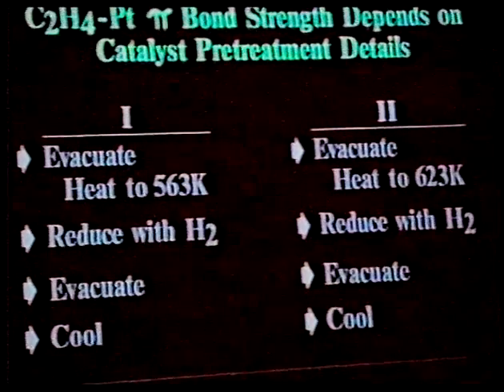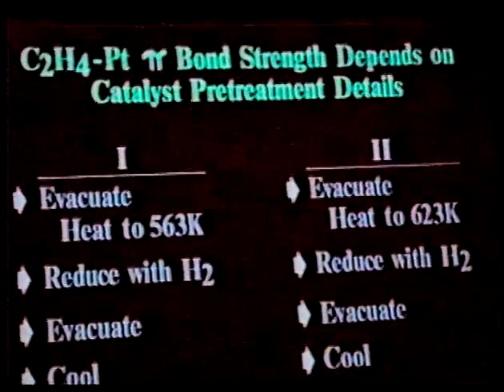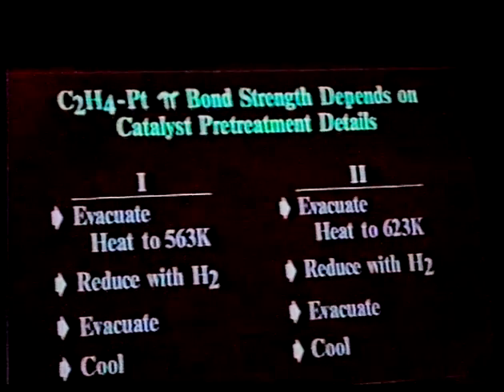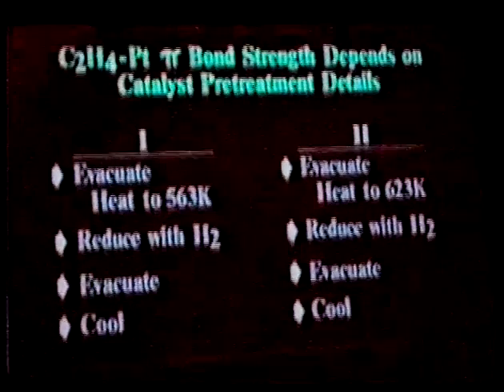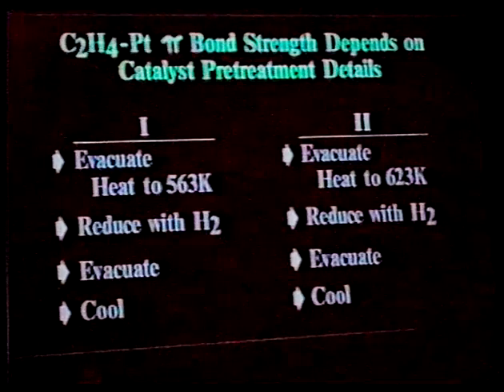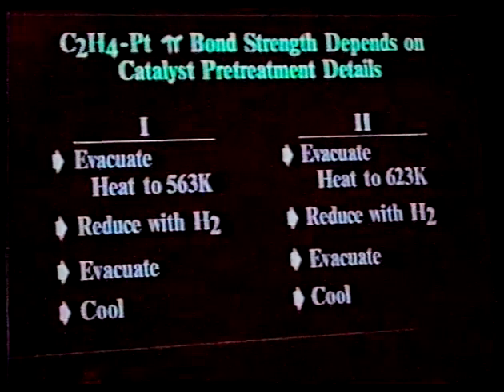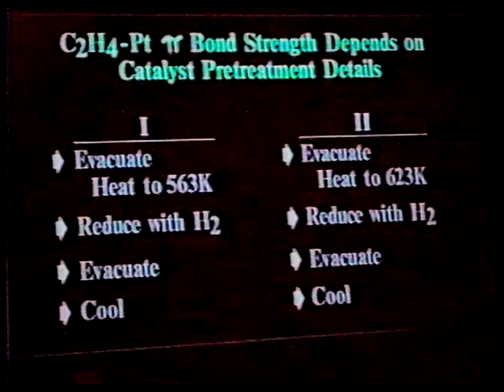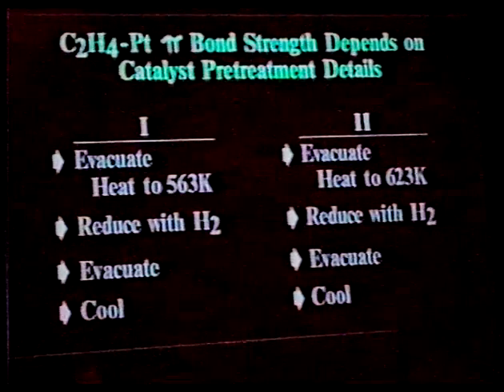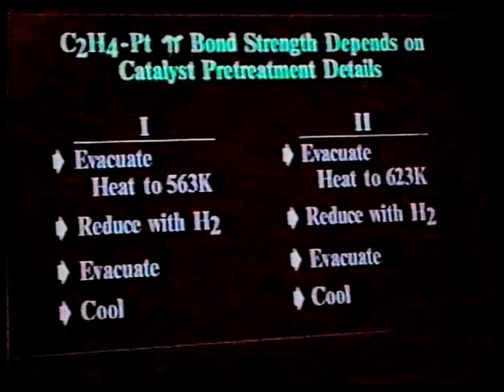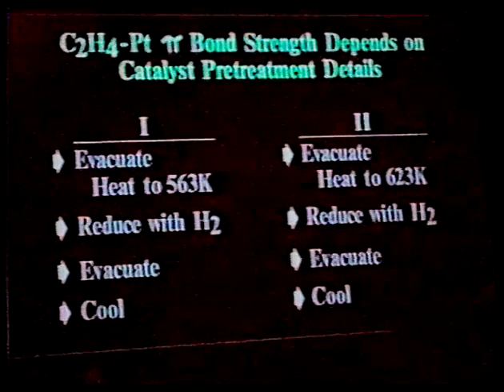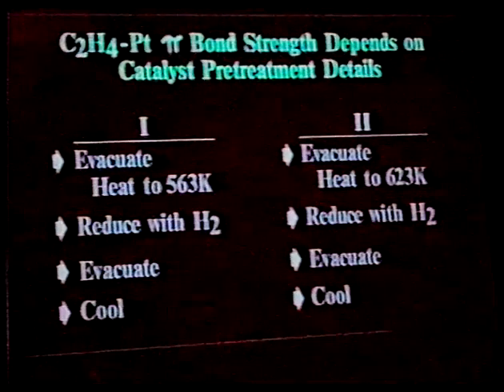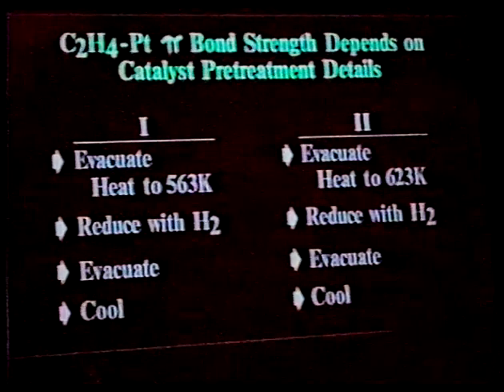Well, let's move on and ask ourselves what happens to the pi bonded ethylene. Now, if we take the initially saturated layer, these are all saturated layers, by the way, all the way from low temperature up to room temperature, we can watch the conversion of the di-sigma bonded species to ethylidyne, and we can watch the pi bonded just sit there. It just does not do anything. However, it does do something very interesting if you change the way in which you prepare the catalyst.